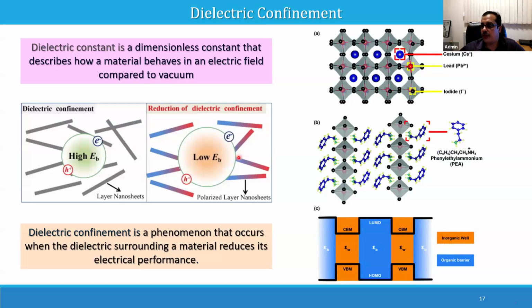Okay, we used phenylethyl ammonium, that is an aromatic one. So earlier we used methyl ammonium, then we used propyl diammonium, both are aliphatic. Okay, so we used an aromatic unit in this case, and these aromatic units can actually polarize. Unlike the aliphatic one, this can relatively polarize, and that polarizability actually reduces the dielectric confinement.